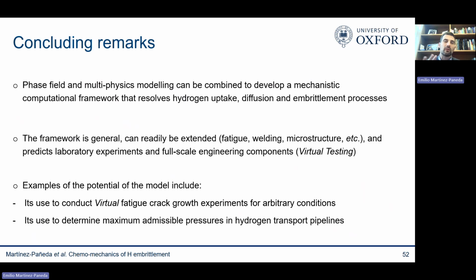I particularly showed two case studies that I thought were quite relevant: the application of these models to predict fatigue crack growth, to conduct virtual fatigue crack growth experiments for any arbitrary condition, and also to determine what is the maximum admissible pressure that we can handle in hydrogen transport pipelines.